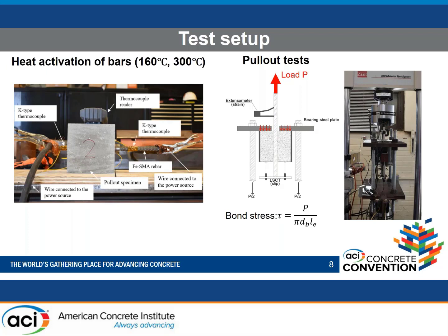So these are two figures from the test setup and the activation process. Essentially, what we did first, we pre-strained all the shape memory alloy bars. All of them were 4% and one series was 8%, just to see the influence, if any, of the pre-strain on the bond behavior. After that, we heated the bar, and the heating was done using an electric current. Essentially, we used a 600 ampere power source. Here I'm showing a K-type thermocouple from both sides, just to make sure that the temperature has reached the target temperature at both ends. You can see this is just an insulating tape in order not to influence the readings of the thermocouple, since we have electric current crossing the bar. And that's it. When we reach the target temperature, we turn the power supply off.